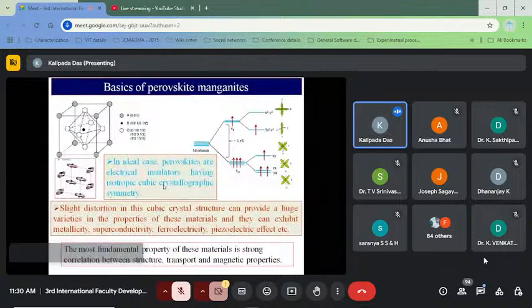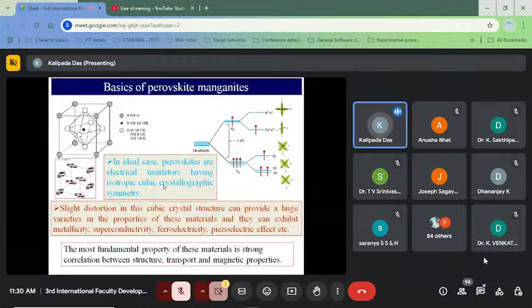Now I will describe some basic properties of the perovskite manganite, because in my whole talk I will talk about the property change in perovskite manganite and properties tuned by some chemical composition change in perovskite type structure. Generally, the ideal perovskites are electrically insulating with isotropic, cubic crystallographic symmetry. But slight distortion of this cubic crystallographic symmetry can provide a huge variety of properties, that means ferroelectricity, piezoelectricity, etc. The most fundamental materials of that type, such as LaMnO3, CaMnO3, etc., all have an antiferromagnetic ground state, and electrically these are insulators.